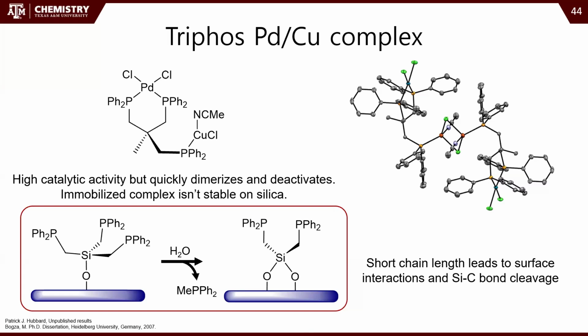Wouldn't that be nice? So we made this, and it doesn't really work that well because it dimerizes. If you make it in situ, it works great for a few minutes until it dimerizes. If you make it and then you put it in, it doesn't work, already dimerized. So we thought, okay, we can prevent this dimerization by just fixing the ligand onto the surface, except the ligand is not stable anymore. So that just gets hydrolyzed and you get methyl diphenylphosphine in solution, and then you have 2 phosphines where you should have 3.